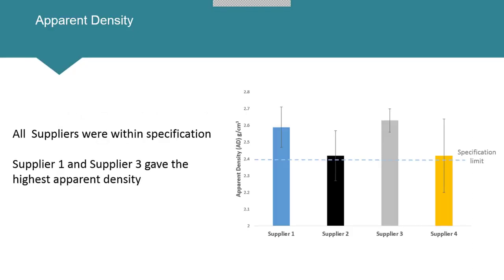Then the final thing we looked at was apparent density. In this case, we can see, probably quite linked to morphology, suppliers 1 and 3 tend to have the highest packing density, suppliers 2 and 4 somewhat lower. Suppliers 2 and 4 are just peeking into the specification limit, but suppliers 1 and 3 are higher, and obviously higher is better, more favourable from that perspective.